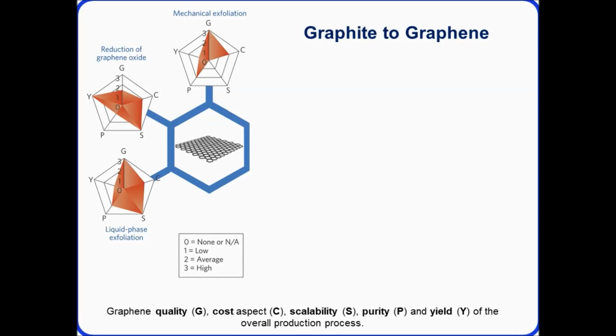The second approach is a more chemical-based approach, called graphene oxide production. Here we would do an acid-based reaction on the graphite powder, which leads to all sorts of functional groups being added, typically oxide groups and carboxylic acid groups, which can make the graphene more soluble. But in fact, we leave a lot of defects behind and added to the structure, which can limit some of the important properties that we're trying to harness. So we minimize the electrical conductivity, and we may lose some of the mechanical strength.